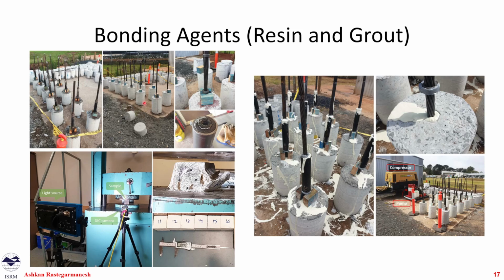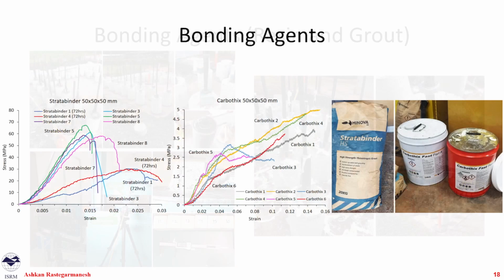And this is the pouring of the grout and pouring of the resin on the right and left. Our resin was a 2-part resin, which was exothermic. You mix them together. It's up to around I think 100 degrees Celsius, and then it mixes together in a few seconds. It hardens, and after some small time, it's going to be fully ready. And there's some testing that we did on the samples.